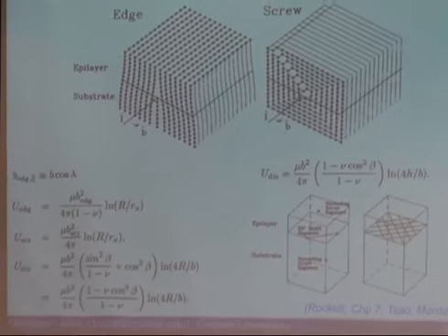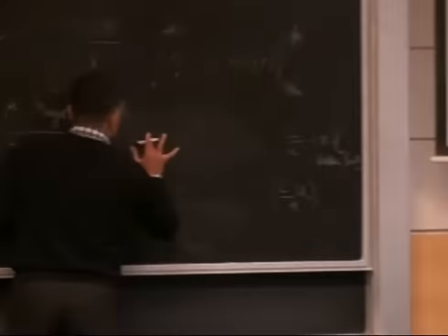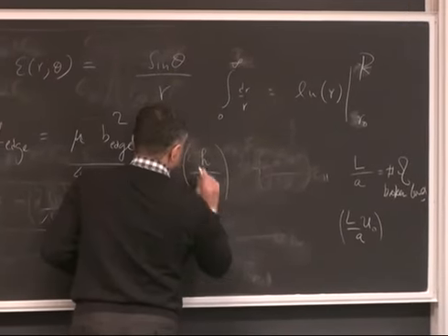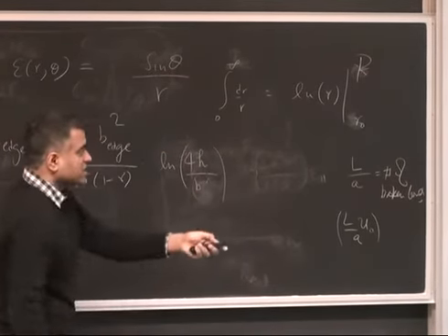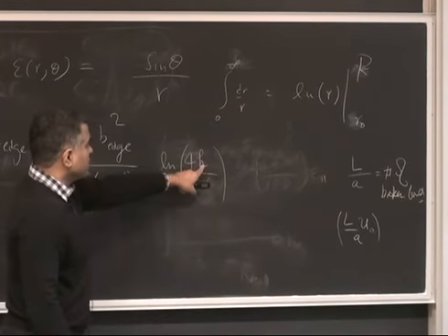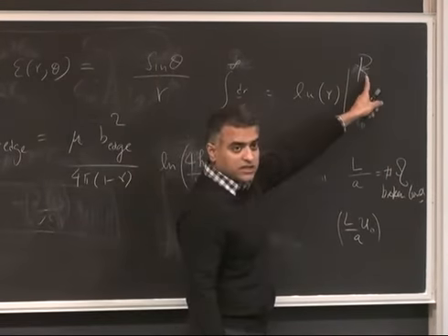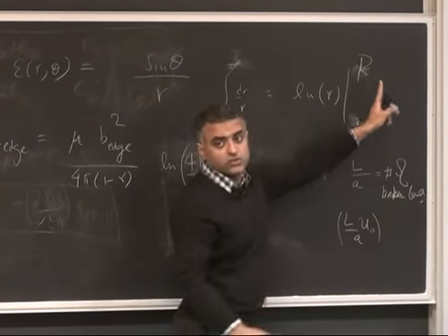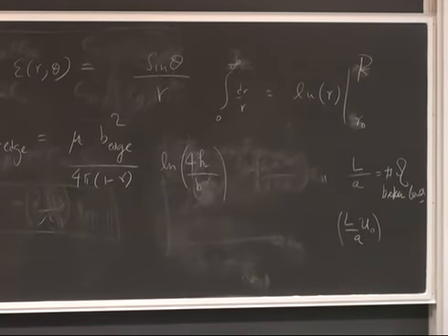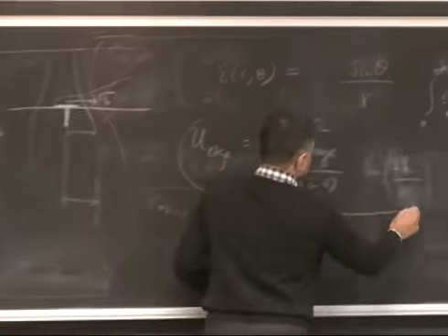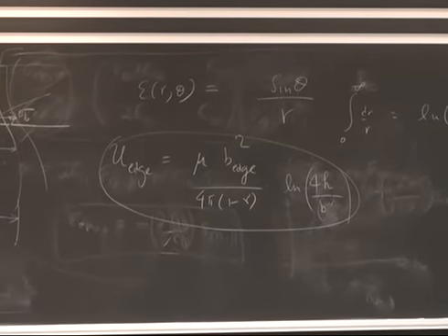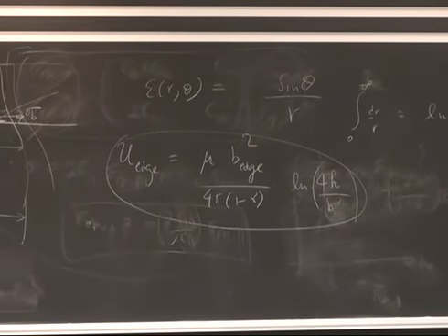Yeah, but those are some of the energy arguments of the dislocation. Okay, so if I have a finite height, let's replace it for now. Natural log of h: meaning if the dislocation is a threading vertical dislocation, then the upper limit is not infinity, it's the thickness of the layer. That's how far it can go, right? So now you basically have two energy scales. One is for remaining coherent, and the other is for forming defects, and you can make a plot of them. The total energy is the sum of the two, right?